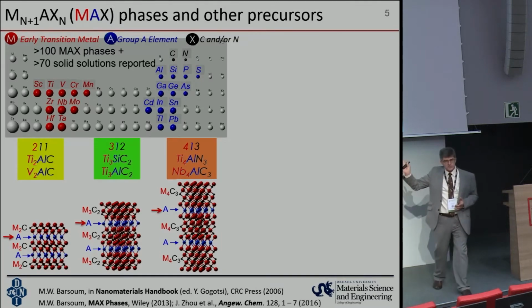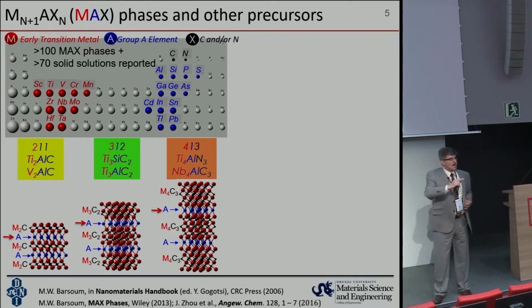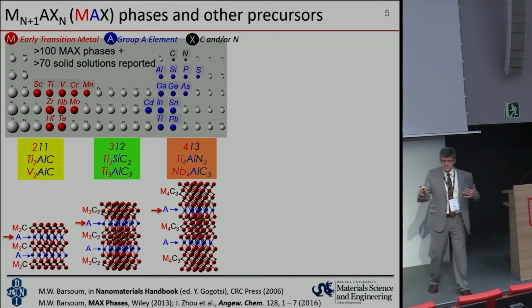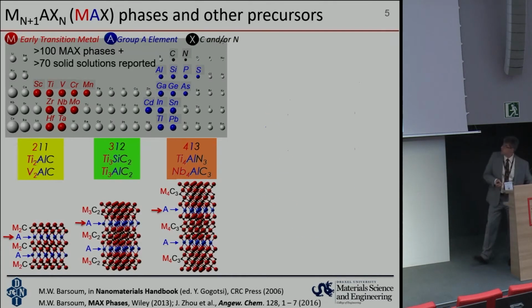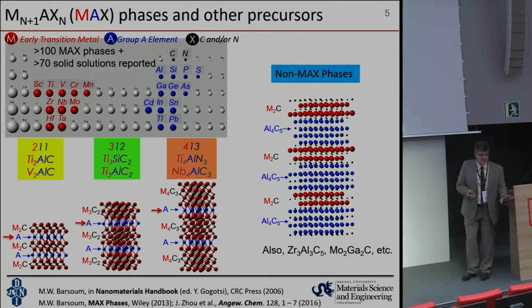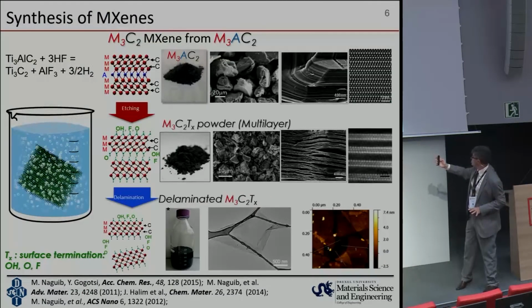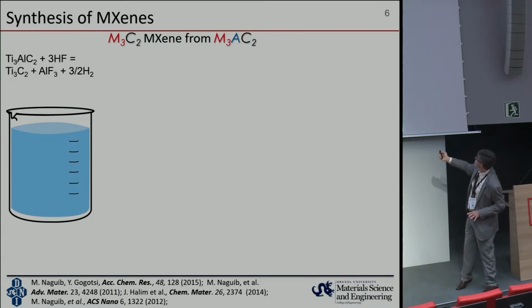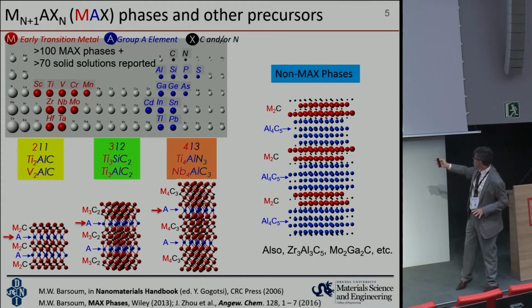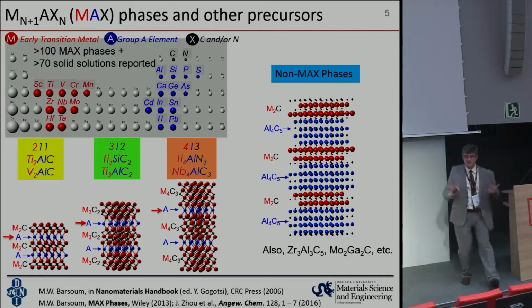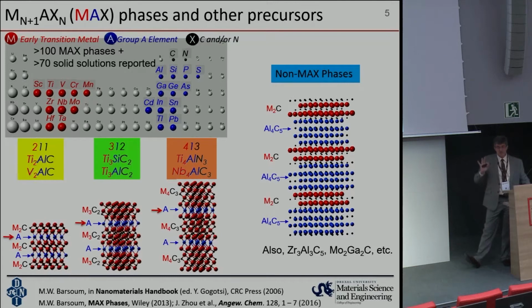What is important here? The bonding between M and A element in these materials is either metallic or covalent, but it's not a weak van der Waals bonding. You cannot simply separate them by mechanical exfoliation. You have to etch those materials. And of course, not only MAX phases are possible as precursors, there are many other layered carbides. Sorry, I have never learned how to use the clicker properly. There are many other layered carbides where you can remove, for example, an entire layer of aluminum carbide, dissolved, leaving zirconium carbide layer behind. There are other similar layered phases which are technically not MAX phases, like Mo2Ga2C. So the message I would like to leave you with is that there are many precursors that open the road to synthesis of many materials.